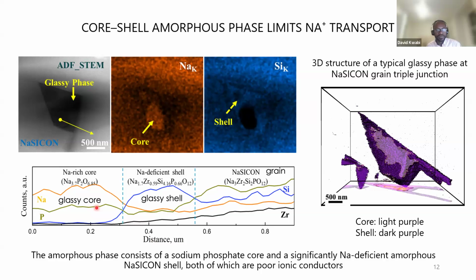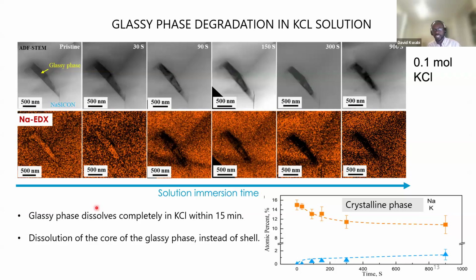One of the nice things about electron microscopy is that you can also see some of the degradation that occurs in very exquisite detail. So this is a series of images showing the glassy phase of NaSICON upon immersion in aqueous electrolyte dissolving over time. We start off on the far left with our pristine material, and then over time we see that the region where the glassy phase is present erodes completely. So we have dissolution of this glassy phase. We know that it's already a poor ion conductor, and we know all of this from very high resolution imaging of the microstructure.